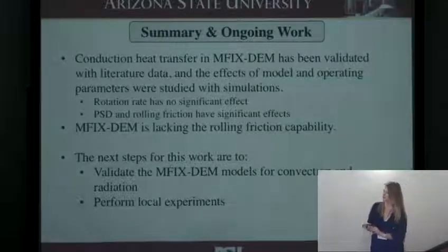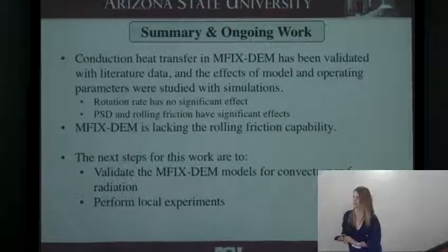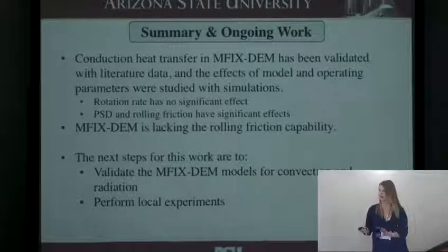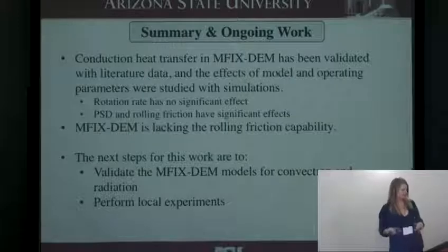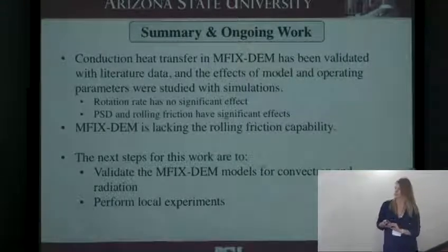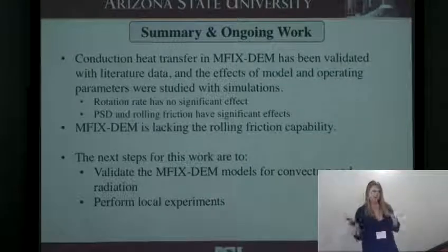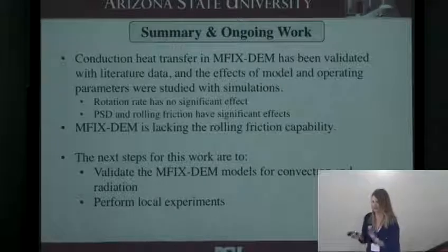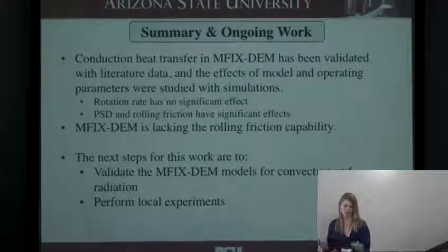We found that rotation rate doesn't have a significant effect, and particle size distribution and rolling friction are important. We identified that MFIX didn't have rolling friction, and we do think it's important for heat transfer. So moving forward, we want to look at convection and radiation and perform our own local experiments.